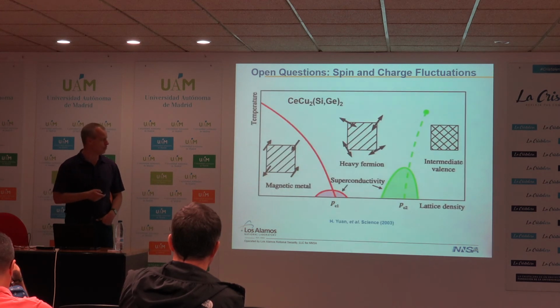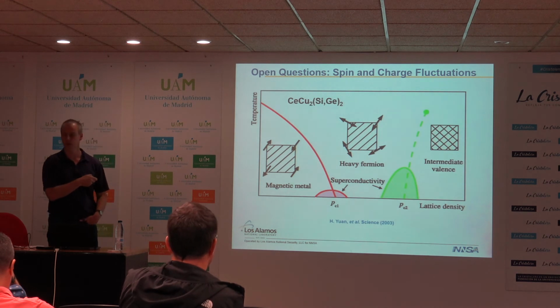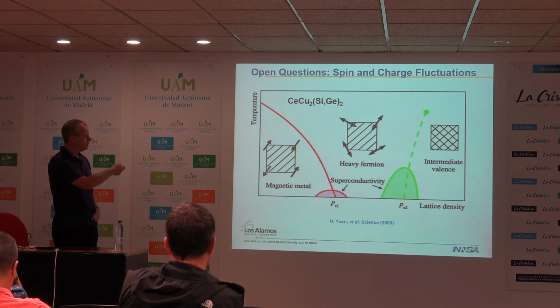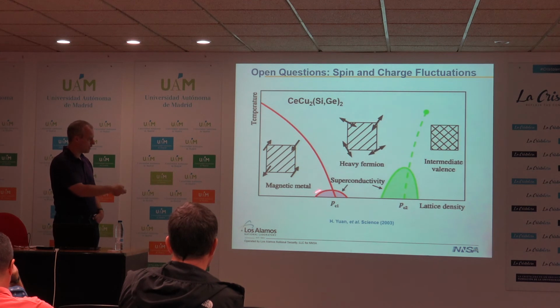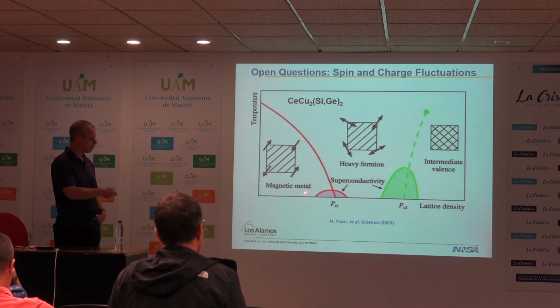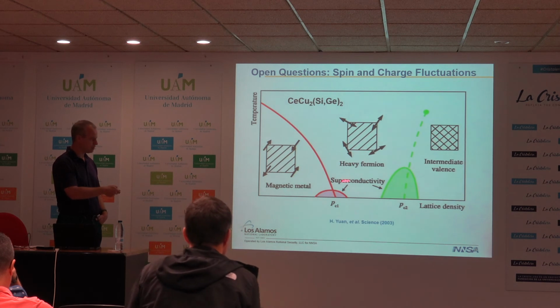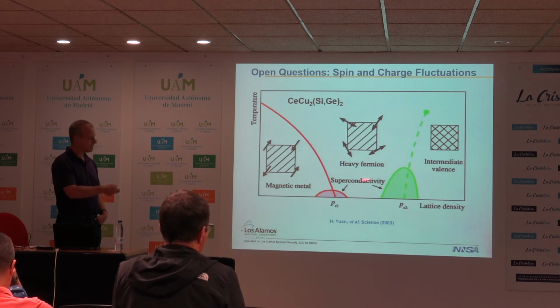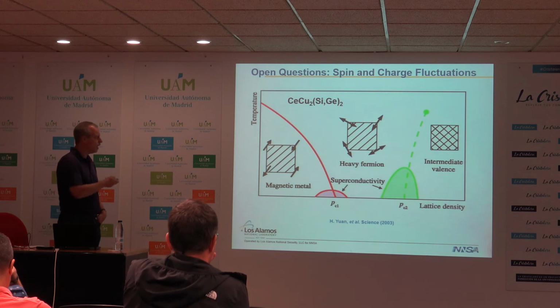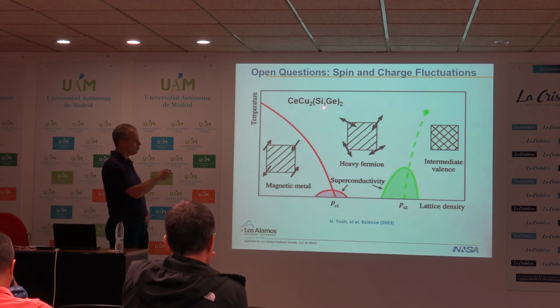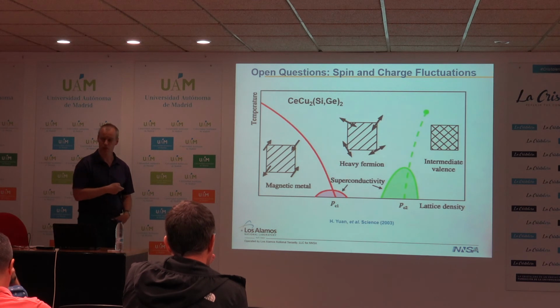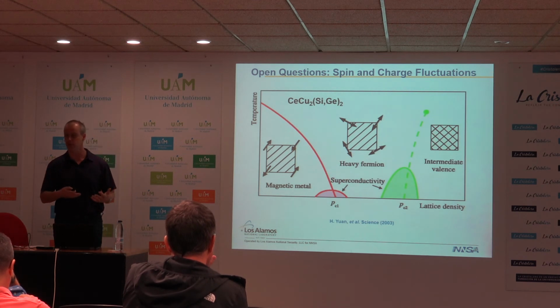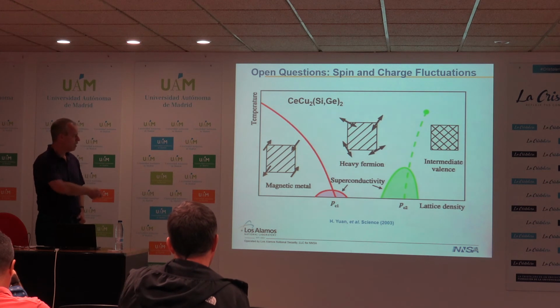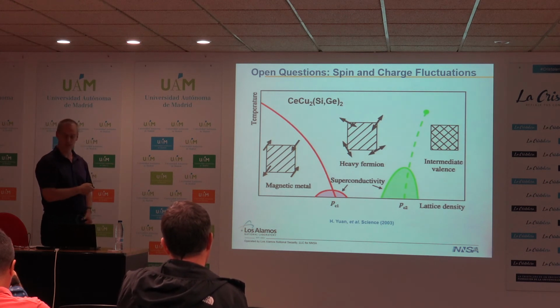And that was really brought out in some work on cerium copper 2 silicon 2. So cerium copper 2 silicon 2 also has the antiferromagnetism and the dome of superconductivity. But in fact, it always had sort of a strange dome, and it's not shown here, but the original dome was sort of a little bit asymmetric and actually sort of looks like it extends to very large pressures. What the group in Dresden were able to do was they doped the system with germanium, okay, and that acted as some form of pair breaking in the system, and it suppressed TC. But they didn't add so much that they killed off TC altogether.